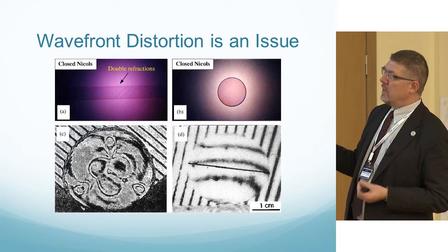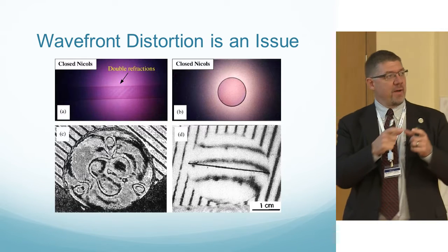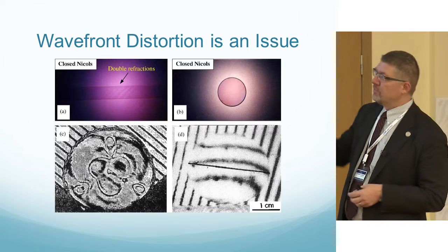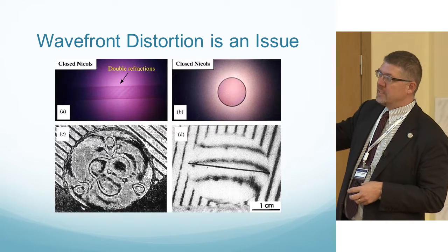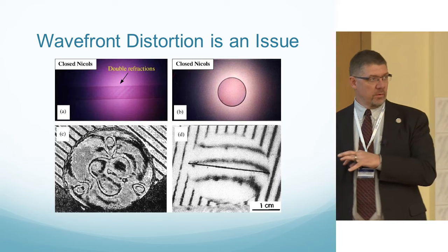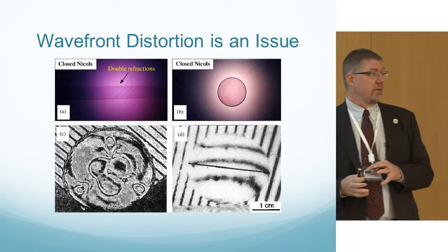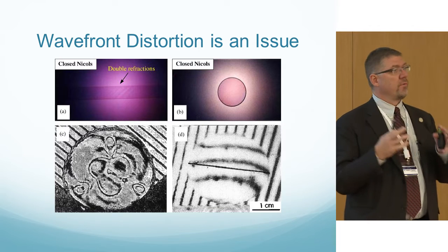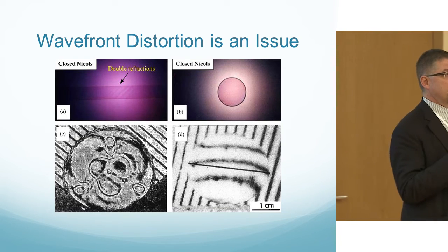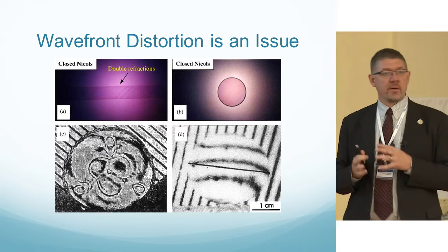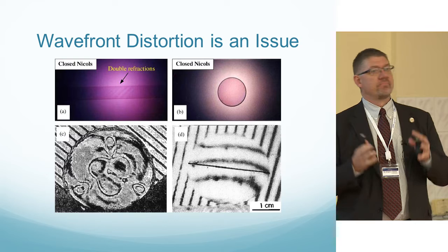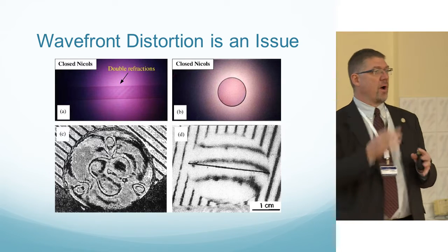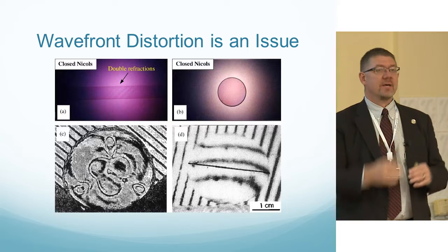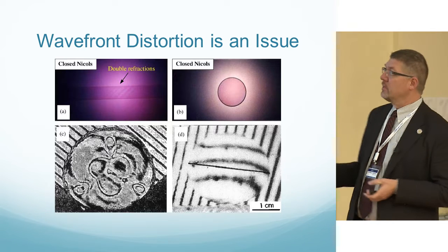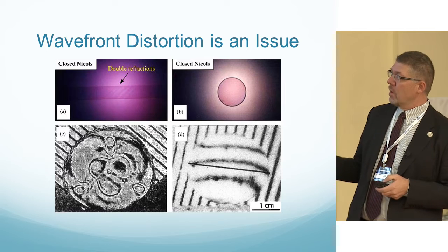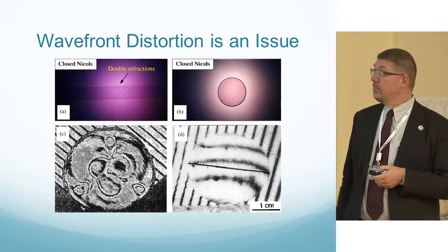You also have very high stress in the very center. So if you're trying to fabricate wide slabs or large pieces of material, you have three small pieces of pie here, if you will. Typical yield with a crystal like this is typically 50 or 60% at best. So you're making all this growth, you're investing all this time, you're consuming kilowatts and kilowatts of power over these 40 days, and you're throwing 50% of it away at the end. It can be done, but that impacts the price of what you see from Coherent and Spectra-Physics and the laser companies that are here. So it is a challenge. You can get decent wavefront out across a 10 millimeter area, but it's tough.